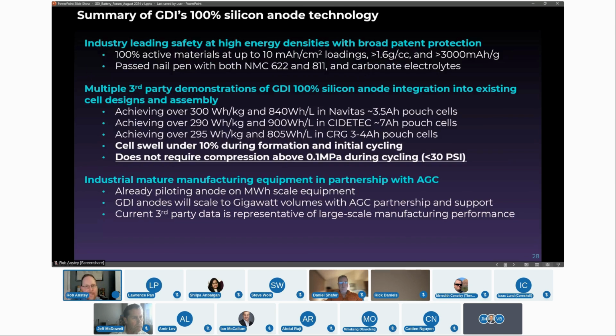And last but not least, in summary, we have shown third-party data showing that we can achieve 100% active silicon. No binder, no carbon nanotubes, just silicon. We've hit areal loadings over 10 milliamp hours per centimeter squared, densities at 1.6 grams per cc and higher. We form our silicon over 3,000 milliamp hours per gram, and then you decide how you want to rate it with N to P. We've passed nail penetration with 622 and 811 with carbonate electrolytes.